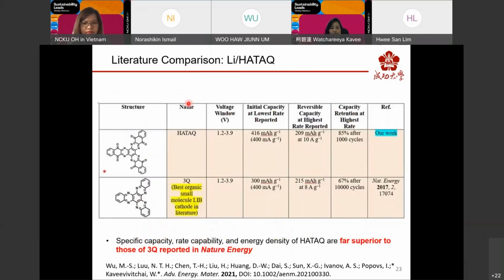Now, comparing the performance to the previously reported work in the literature, we found that with this new structural design, we can achieve much higher initial capacity, and it allows much better rate performance. And this work has been published recently this year in Advanced Energy Materials.